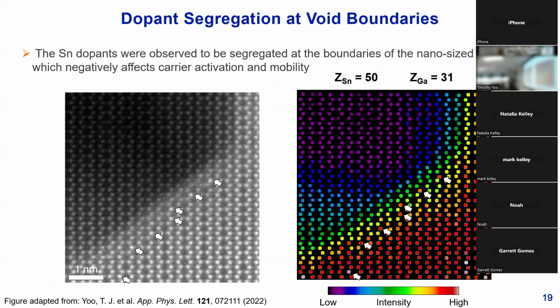We can see that indeed, again, marked by the white arrows here on the right side, these atomic columns are significantly brighter than their neighboring ones, with no sign of any sort of gradient in the immediate area. They just happen to be much brighter than this. And so what this tells us is that actually the tin dopants that were implanted into this film in the first place are being segregated at these atomic column positions near the boundary, given that the tin dopants' Z number is going to be much higher than that of the gallium.